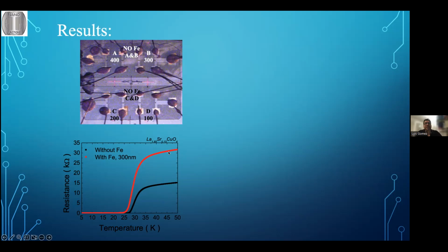So this is the type of measurements that we obtain. If we do the resistance versus temperature characteristics for the sample that has no iron, so either this one over here or this one over here, we'll get a transition similar to the ones that I showed you earlier, but in this case, the drop of resistance will occur about 30 kelvins. But then if we measure the same one, in this case, I'm showing you for this sample that has the 300 nanometer width iron strip, then what we see is that the resistivity before the transition is much higher. And also when it started to drop, it's about the same temperature, but it becomes fully superconducting at much lower